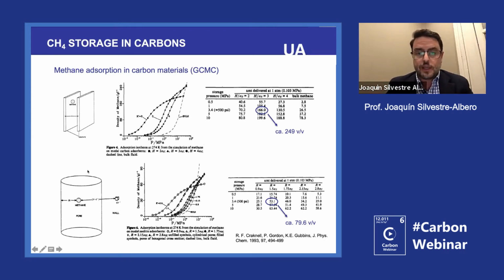And there was also something nice. When you compare this performance with the silica or with the zeolite, which is at the bottom, you can see that the adsorption capacity of the zeolite, the predictions are much smaller than the ones that you have in the carbon. So this is beautiful because it is showing that if you are able to make a carbon with very narrow cavities, you must get a maximum packing density of the methane molecules, and you must be able to be very close to the DOE target.